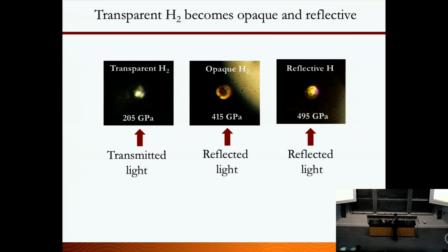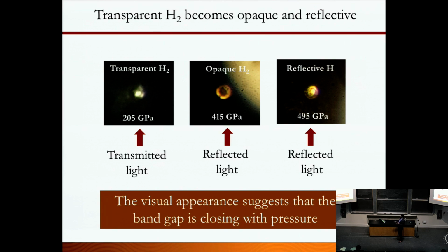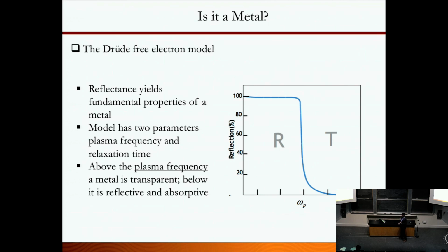If you squeeze further, you will see it get reflective. This is from the reflected light. So the black area is now almost as reflective as rhenium, or even higher than that, right here. Visually, you're seeing that the band gap is closing. So you're seeing an insulator-metal transition. How do you prove this one? We fit this to a Drude free electron model. The theory predicts that it closely follows the Drude free electron model.